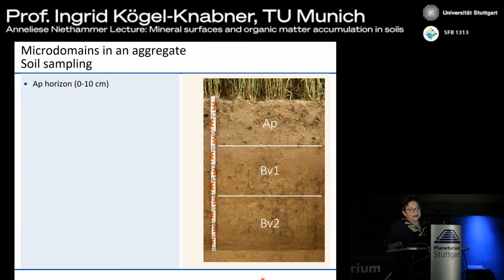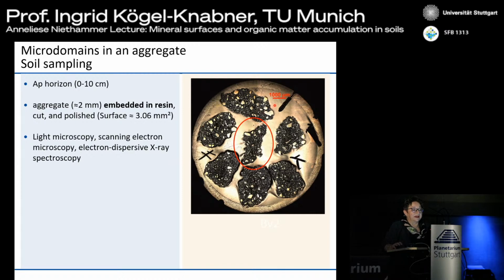And in this case, we did not disperse the soil, but we isolated aggregates. These are the aggregates. This is 1,000 micrometers. So these are larger aggregates that we isolated from this soil. We embedded them in resin and cut and polished the surface. And as I have mentioned, polishing is very important for NanoSIMS because otherwise the data are not very good and the resolution goes down. And then we always do light microscopy, scanning electron microscopy, and we look at the element composition. And we also did NanoSIMS analysis with this aggregate here.